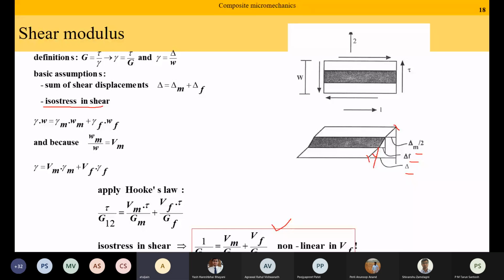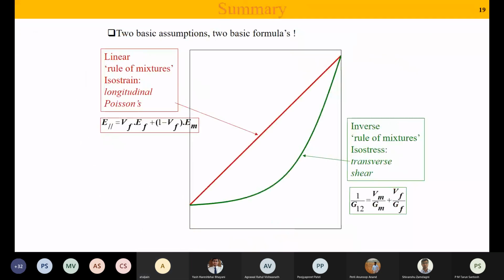But for the time being, let us say that we have made this assumption that the stress in the fiber and the matrix is going to be the same, so it is isostress. Based on this assumption, we calculate that the shear modulus is actually an inverse rule of mixtures. So the shear modulus increases in a non-linear fashion as I increase the fiber content. So broadly speaking, all the different properties of a unidirectional composite are going to follow one of these two trends. Either it is going to be a linear rule of mixtures, for example, the longitudinal modulus or the in-plane Poisson's ratio nu 1,2, or it is going to follow the inverse rule of mixtures, for example, transverse modulus, shear modulus.